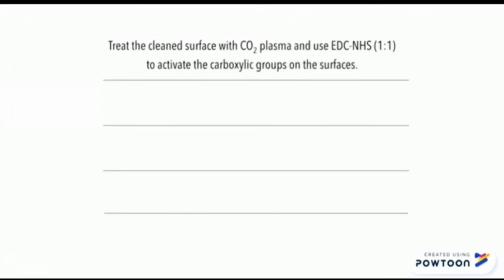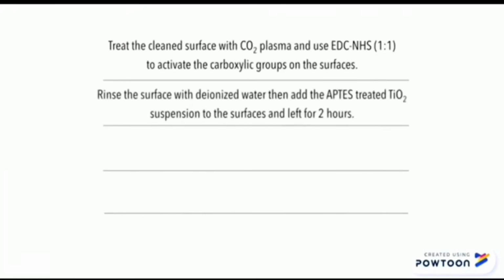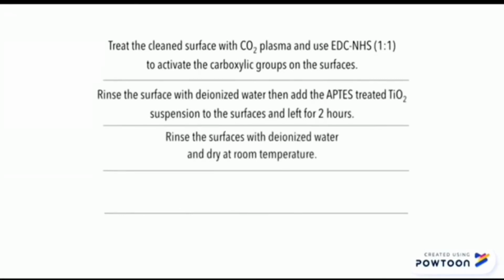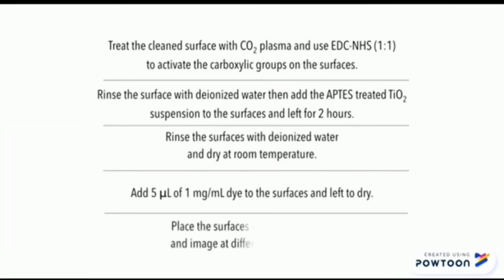Then treat the clean surface with CO2 plasma and use EDC NHS at a 1:1 ratio to activate the carboxylic groups on the surface. Rinse the surface with deionized water and add the APTES treated titanium dioxide suspension to the surfaces and leave for 2 hours. Rinse the surfaces with deionized water and dry at room temperature. Add 5 microliters of 1 mg per 1 ml dye to the surfaces and leave to dry. Place the surfaces in the UV chamber and image at different time intervals.